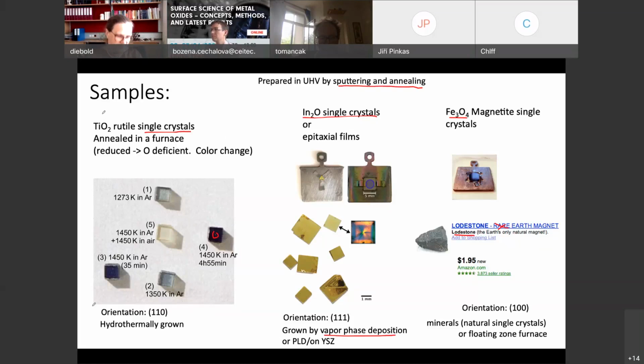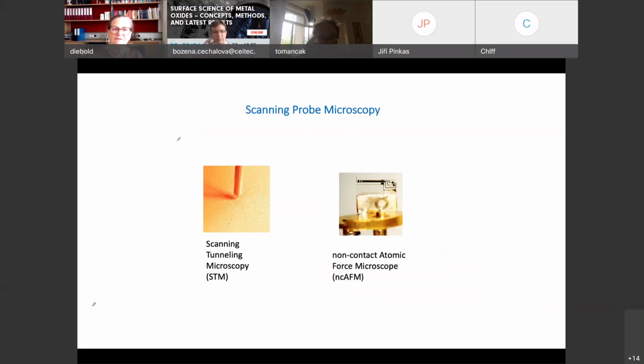Now let's talk about TiO2 next. And let's look at how we can use scanning probe microscopy, so scanning tunneling microscopy and atomic force microscopy, to look at it. So this is the end of the sharp needle that I've shown you. It's in what we call tunneling contact, a few angstrom, half a nanometer in front of the surface. We have a voltage between tip and sample. We have a tunneling current. We keep the current constant. And we gently stroke the surface back and forth, and this motion of the tip will then be transferred into an image. So that's scanning tunneling microscopy.